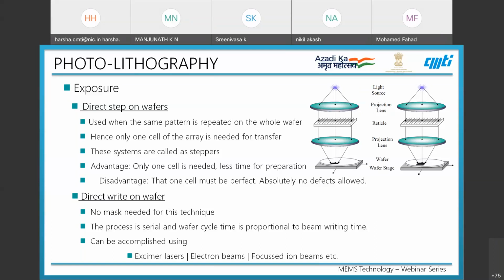The other method is direct write on wafer, where no mask is needed for this technique. The process is serial, and the wafer cycle time is proportional to the beam writing time. So instead of a light source, in direct write on wafer we use a laser, an electron beam, or a focused ion beam to write those patterns from the design file directly onto the wafer. The wafer cycle time depends on how fast the laser, electron beam, or focused ion beam can perform the writing operation.